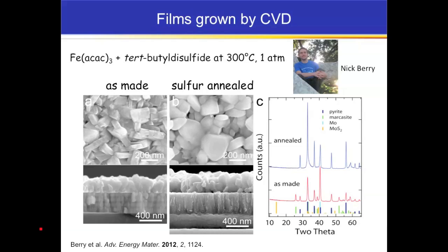Just to show you a little bit about what we do with the thin film materials, this is our chemistry used for growing pyrite thin films by chemical vapor deposition. We use iron ACAC and tert-butyl disulfide. The process is at about 300 degrees C. After we do sulfur annealing of the film to convert the material completely to pyrite, we get a morphology that looks like this from the top down and from the side. This material was deposited on molybdenum-coated glass, which is one of the contexts that we use for device development.